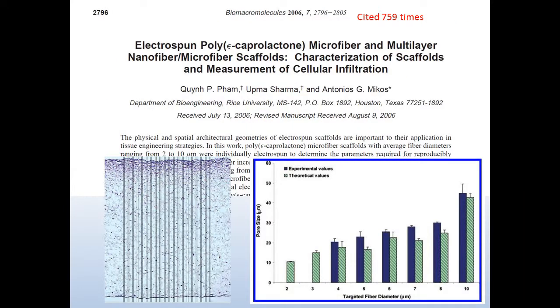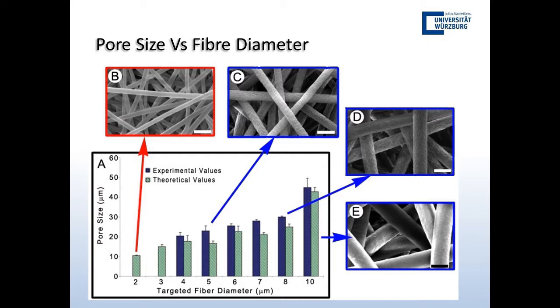I think Tony Mikos and colleagues looked at what happens when you get fibers of different diameters and randomly deposit them upon each other. If you have a 2-micron diameter fiber, then the pore size, if you just have random deposition, is about 10 microns. And it wasn't until you got to about 4 microns that you started getting 20 micron size pores. And this is actually also a highly cited article. And so you can see that the pore size with the small fibers versus the larger ones are much larger. There's much more pore size in here.